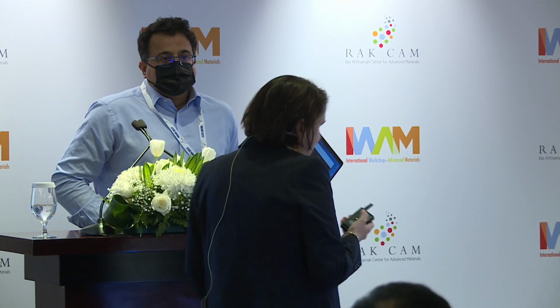Very interesting work. How much enhancement is there in the catalytic hydrogen evolution reaction, and how much magnetic field is needed, and is it a systematic enhancement by field strength? So we didn't do the real full systematic study. We started with a simple magnet. The last measurements with the crystals were with a real big magnet. We have a 7 Tesla magnet now where we can tune the magnetic properties. Before, we simply applied a hard magnet. So the magnetic field we measured was 0.3 Tesla, and we saw an enhancement of a factor of 2 in the Weyl semimetal.